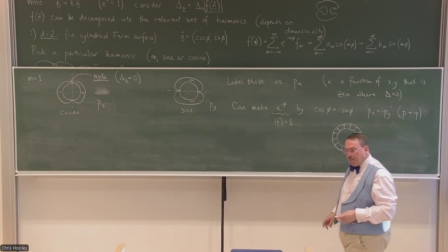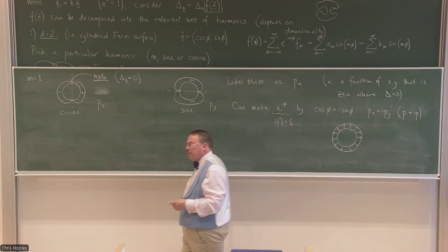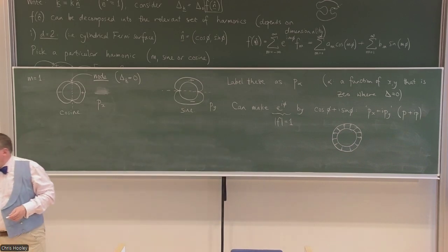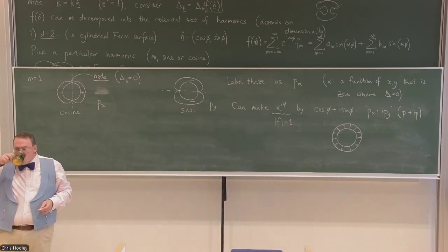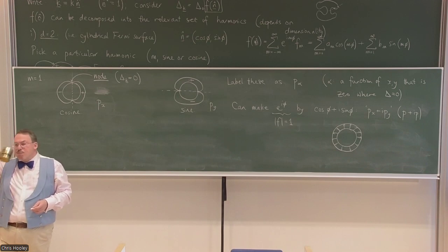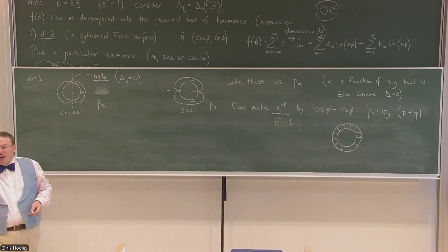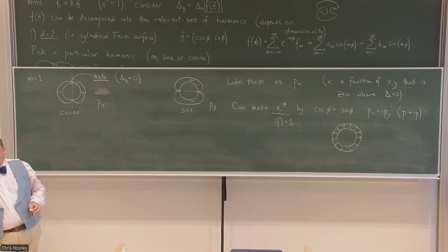And this has real physical consequences, because for many purposes, px plus ipy will give the same thermodynamic responses as s. Right, exactly. So if all you care about is the energy gap, and all you can measure is the energy gap, those two will look the same as each other. You'll have an exponential suppression of the specific heat capacity at low temperatures. And you have to look quite carefully to see what the difference is.